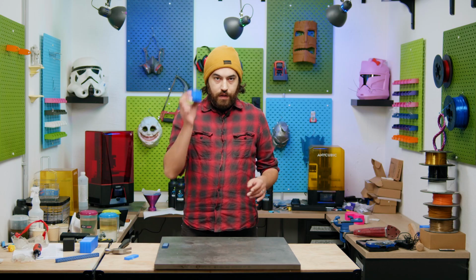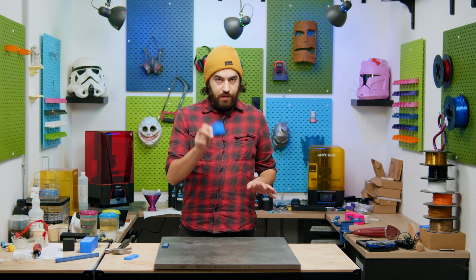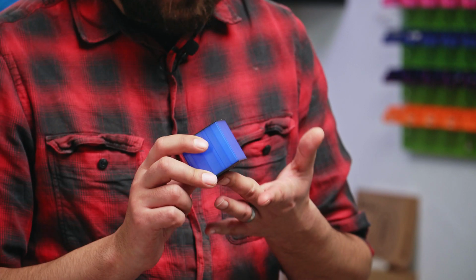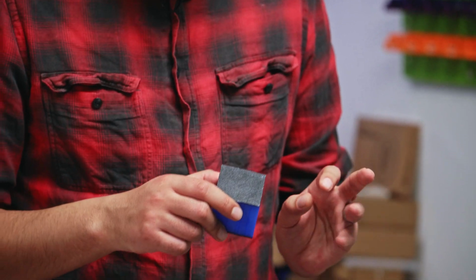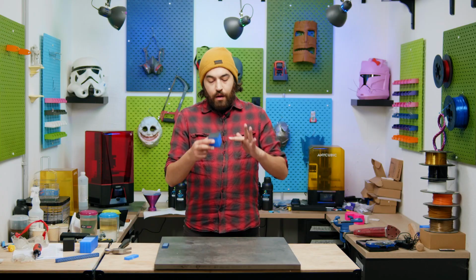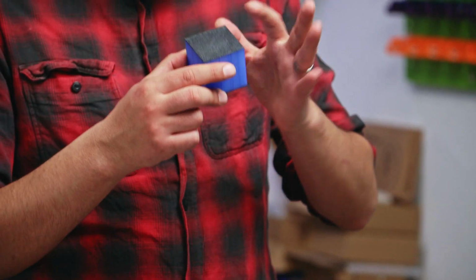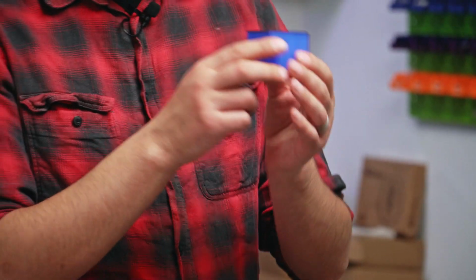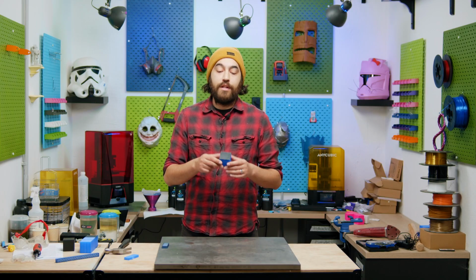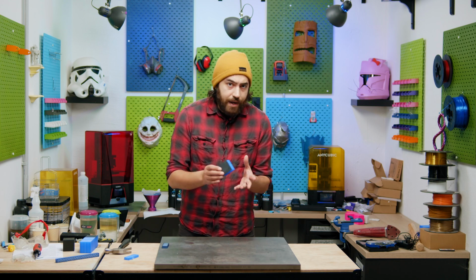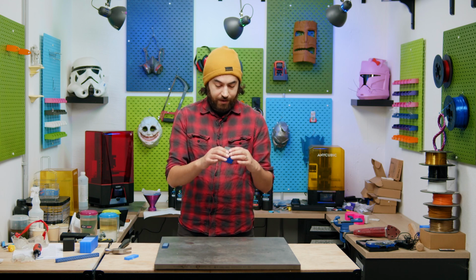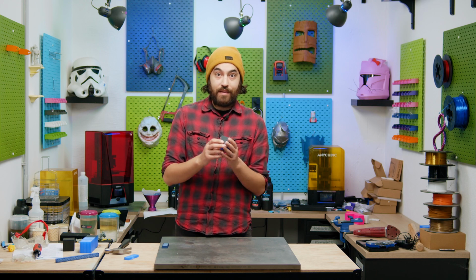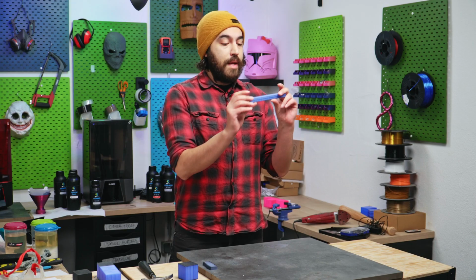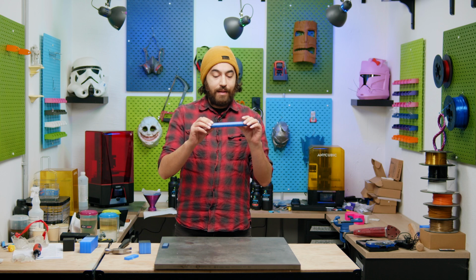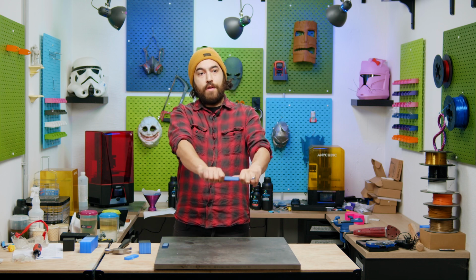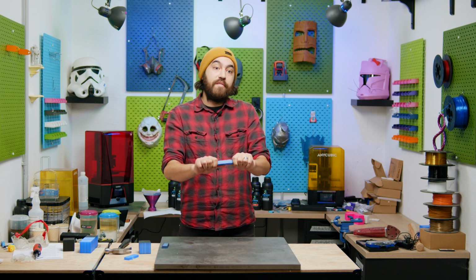Let's go from there. So this is our test piece. It's just a normal cube, but on the bottom we have 2 layers of PETG and then 3 layers of TPU. The rest is pretty much PETG until the top, where we get to another 3 layers of TPU and then 2 layers of PETG to cap it off. I mean, all we're doing here is putting on a cushioning layer for protection. Hopefully that's going to be enough so that it can actually survive our tests. I also made a longer one with a central band and it's quite rigid. The slab has a tiny, tiny bit of flex to it.